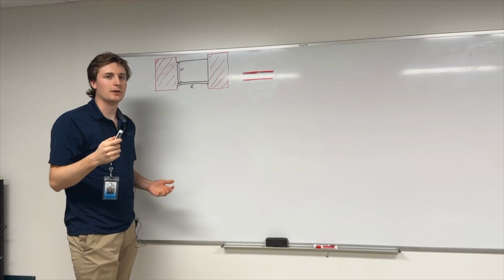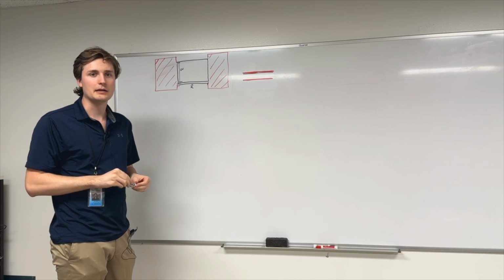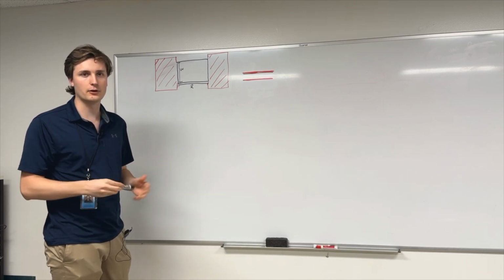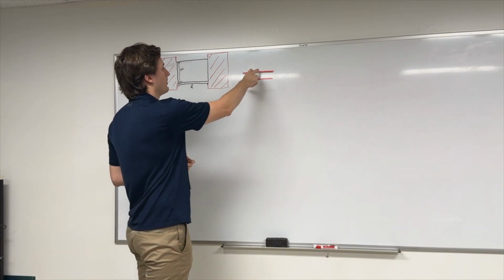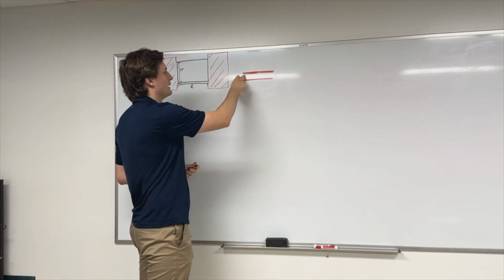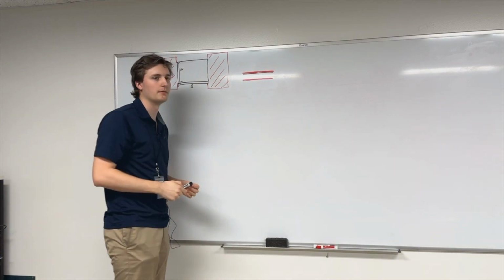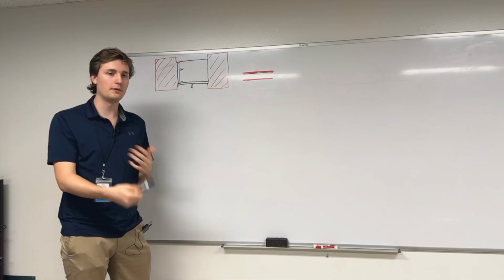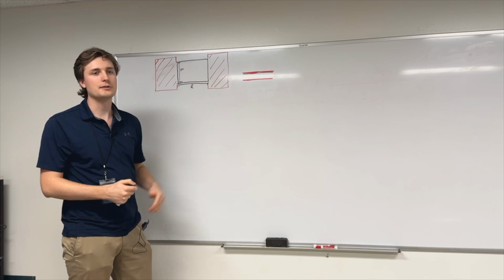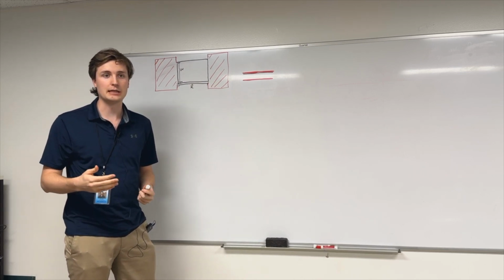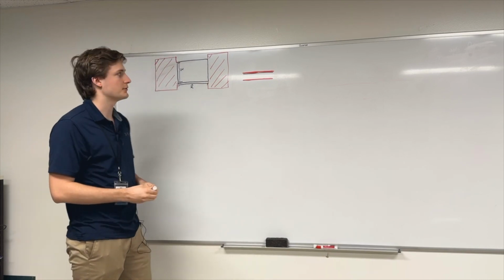So first thing I want to sort of emphasize and address is the very basic level on what the embedded passive, its critical properties are. So we start with an inner layer, copper clad, and between the dielectric and the copper cladding we have a very thin layer of this resistor material. It can be nickel phosphorus, nickel chrome, chrome silicon oxide, any sort of material depending on what the customer needs that ohm per square value to be, however much resistance they need in this resistor.